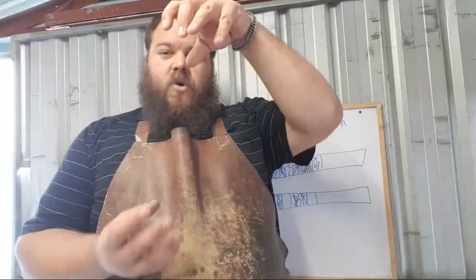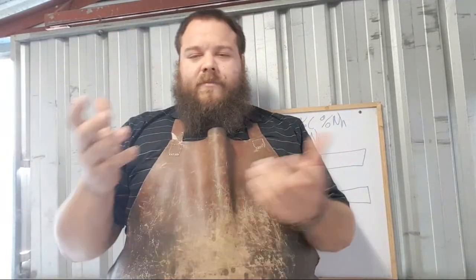The problem is that the taller your billet, the more pillar stress you have. So you end up with a pillar that's going to collapse, and that makes it really difficult to forge weld. And that's what a lot of people find out when they do feather patterns, because you need to make the billet quite tall and wide in order to be able to cut the feather. And having anything that's tall and hot when you try and upset it, which is what you're doing when you're forge welding from the top, you end up with a lot of pillar stress, which means that the pillar wants to buckle. And if the pillar buckles while you're forge welding, that forge weld is just going to give way and you end up popping the billet in two.